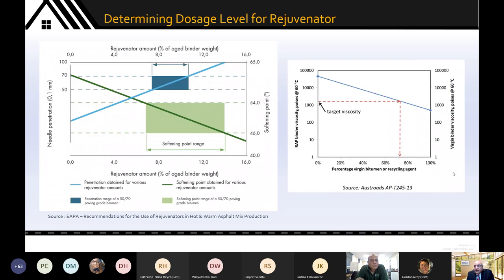There's also a school of thought that says we should look at the liquids, at the bitumen, and determine dosage level for rejuvenators based on bitumen data. The first part of this comes courtesy of the EAPA, and they were looking at softening point and penetration. They did it as a rejuvenator as a percentage of RAP binder. You could do it as a function of that. You could do it as a function of mixed RAP plus virgin binder, really whatever works for you. And what you're looking for is the sweet spot in softening points, sweet spot in penetration, and that will tell you your dosage of rejuvenator that you should be using for your mix.